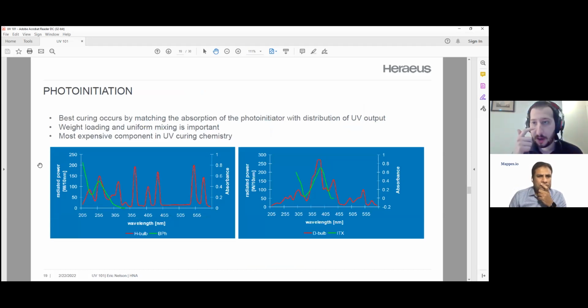So here's a little bit about photoinitiators and how they work. Like I mentioned, the photoinitiators are the UV reactive part of the chemistry. So basically, by mixing a small amount of UV reactive particles into a mixture, you can create a chemistry that reacts to UV energy and that changes when it's hit by UV energy. And how this is done is we try to match up the absorbance of these photoinitiators with the output of the UV lamp. There's many different types of materials that could be used as photoinitiators, and they would be selected for different reasons, just like you might choose a coating where you're trying to get different properties. Some photoinitiators are better for hard coatings, some are better for printed inks. It depends on the end result. It depends on how fast you're trying to go, and also on the cost of the materials. You might select one photoinitiator over another.